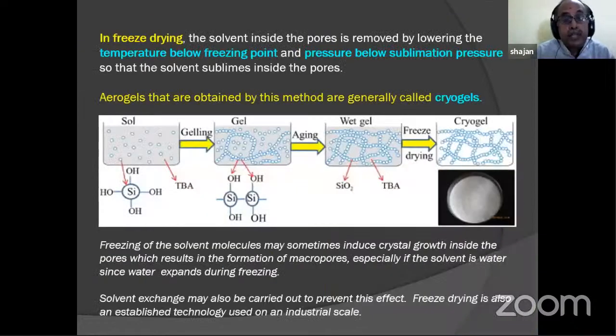The second method is the freeze drying method. Here it is just the opposite, you have to lower the temperature. We have to lower the temperature below the freezing point, and also simultaneously you have to keep the pressure below the sublimation pressure. Both are important. So this is also an industrial process like the previous one, the supercritical method. Freeze drying is also done in many industries for production of bulk amounts of aerogels. So you reduce the temperature below the freezing point and the pressure below the sublimation pressure.